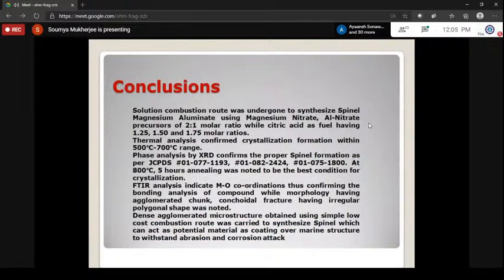and XRD analysis has shown the successful phase formation, where the temperature range has been confirmed from the thermal analysis. The thermal analysis indicates the crystallization within 500 to 700, but we have deliberately increased the temperature to have a proper phase formation. But this temperature is much lower than solid state sintering, which is around 1500 degrees centigrade.